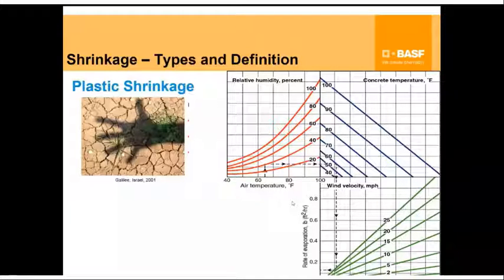But before I start, I want to make it very clear that all shrinkages happen because of movement of water. This is the primary reason. There's no other reason. All shrinkages in concrete are happening because of movement of water. Plastic shrinkage happens because of movement of water out of the concrete into the atmosphere, also called evaporation. You can see that in soil, in the image that I have shown. You can see that in your clothes when you dry them outside in the sun, they become wrinkled. So those are all examples of plastic shrinkage coming from evaporation of water from the substrate.